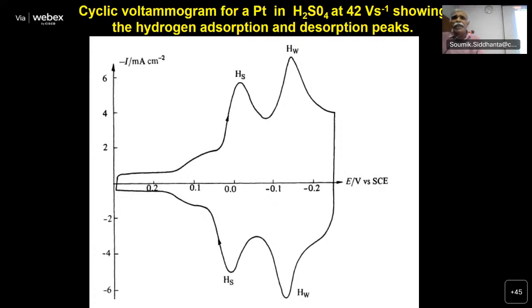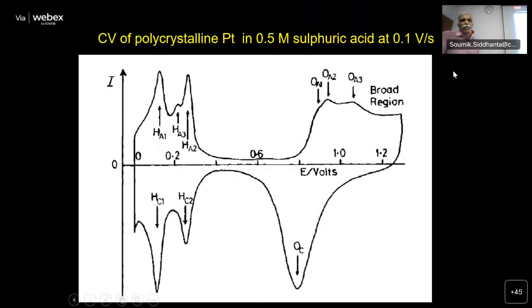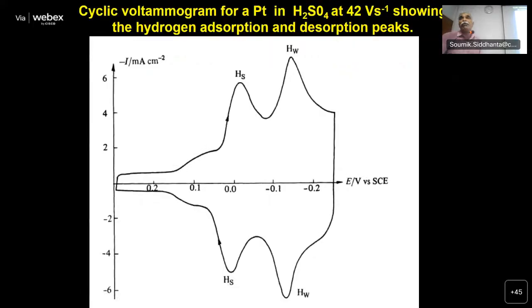If you don't understand quantitatively, you can also do a lot of work, electrocatalysis. Look at this cyclic voltammogram. This is what is called, you see the peaks. Butterfly pattern in cyclic voltammetry. Why is it butterfly pattern? Look at the potential. This is sulfuric acid only. This is a cyclic voltammogram of platinum, polycrystalline platinum in sulfuric acid at a particular scan rate. Remember the potential region, plus 0.2 to minus 0.2. Very small, narrow region. Why am I interested in this region?